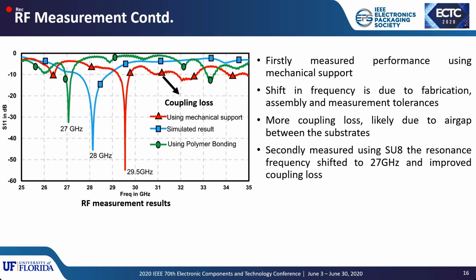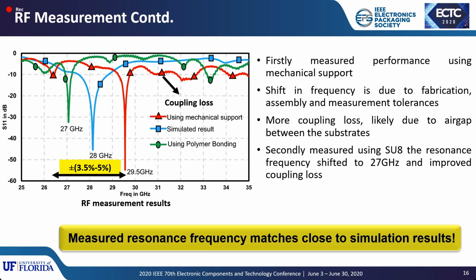lower frequency points. From the measurements, it can also be observed that the shift in the frequencies from the simulated results is between 3.5% to 5%, which is under the tolerable limits. So the measured resonance frequency matches very closely with the simulation results.